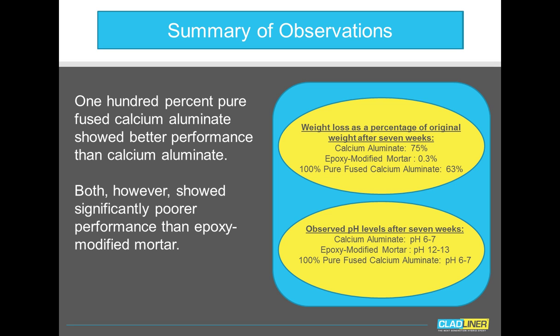As far as the observed pH levels of the cores go, calcium aluminate was between 6 and 7, which is just below neutral. The 100% pure fused was also between 6 and 7. The epoxy-modified mortar, however, was in the 12 to 13 range, which is very highly basic, which is very, very good for the strengthening properties that you want to see in concrete.